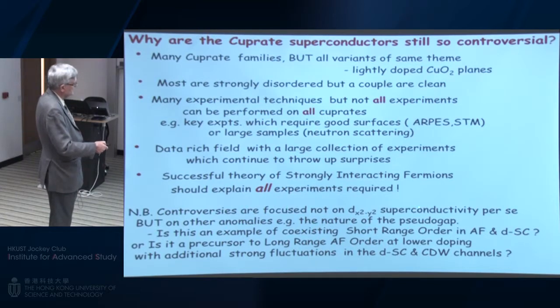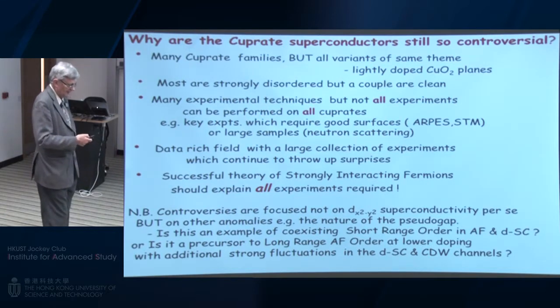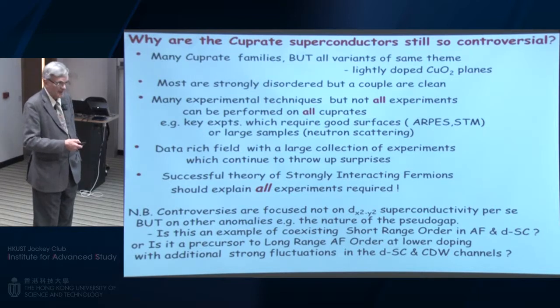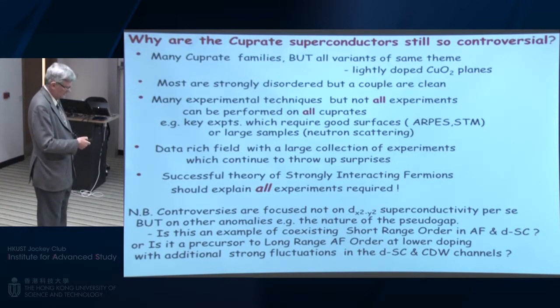As I said, the controversy is not so much on the superconductivity per se, but also, for example, on the nature of the pseudogap, which was on the previous slide that I showed you, where the superconductivity in the underdoped region went down, and where we made a transition to a precursor of this Mott state. And yet this whole business of reorganizing the Fermi surface seems to occur with short-range order. There are many different points of view, and Fuchun Zhang and I, during our time here, have been discussing this problem. It's still a problem, the pseudogap, and certainly there is no agreement today.